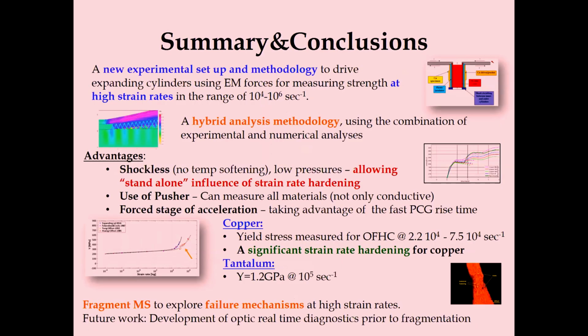So just to summarize, I showed you here the new experimental setup and methodology to look at strength at very high strain rates. The advantages of this technique, again, it's shockless, so we're looking at low pressures, there's no temperature softening, and this is allowing a standalone influence of strain rate hardening, and that makes it very desirable. We use a pusher so we can measure all materials. It doesn't have to be conductive, and we're looking at the forced stage of acceleration, and that's how we're taking advantage of the very fast behavior of the pulse current generator. If you have a faster pulse current generator, you could get even to higher strain rates.